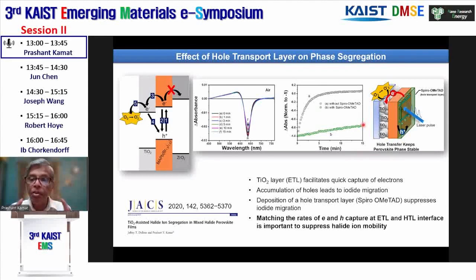And the thing that is important here is, in a perovskite solar cell, while designing your electron transport layer and hole transport layer, you should take precaution that both are pulled out at the same rate to maximize the performance. If one of the rates goes down, then you get accumulation of the opposite charge. And as a result, you can see the decreased performance. Again, in zirconium oxide, we don't see that behavior in air compared to this one. This is, again, showing you here the schematic diagram, and you excite it. If you block the electron transfer, then they recombine and there is no accumulation. If you transfer the electron and scavenge it away with the O2, then you start seeing segregation.